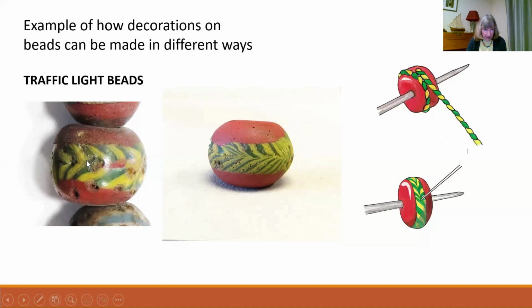This one, can you see there's a gap there in the red between? This one was made like this: twisties done in two different ways, a bit like a Z twist and an S twist. You would have to twist in the two different ways and make two different twisties, and then lie them side by side on your bead. Here, you lay one twisty, a wider one, and then while it's still hot and molten, you drag a needle through. You can see how the needle has dragged through.